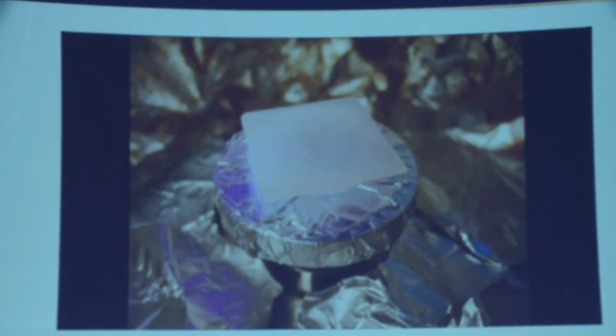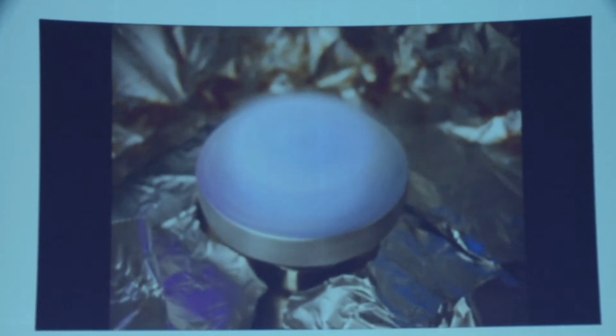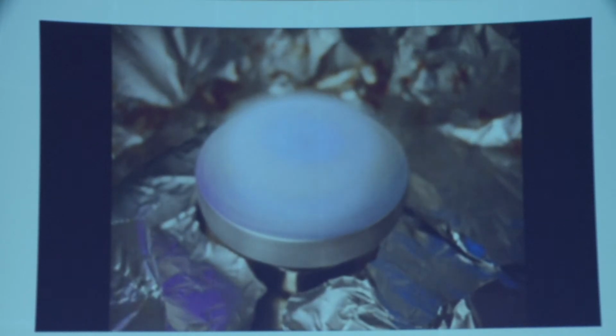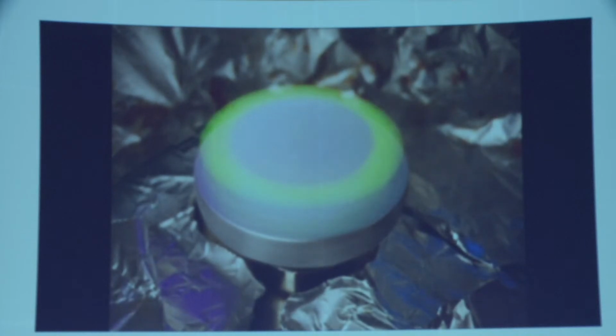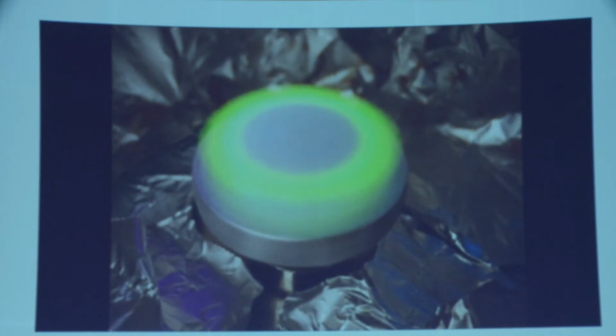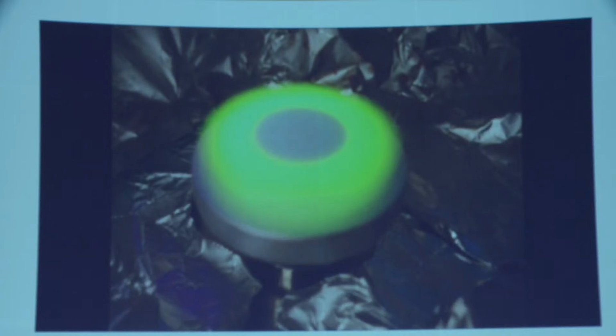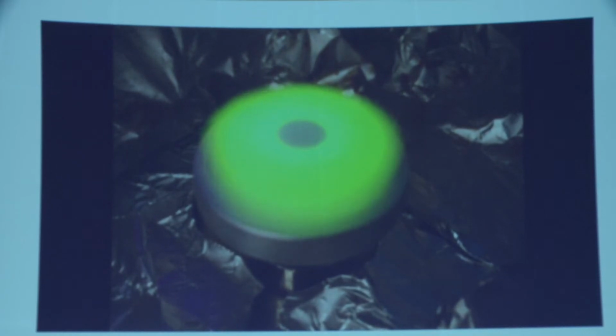It's just a salt dissolved in a solvent. And as it spins, it suddenly starts glowing. This is the perovskite nanocrystals forming on the porous titania. It's glowing - they're re-emitting light. Within that time, those crystals, that layer, has already formed this interpenetrated network of glowing crystals.